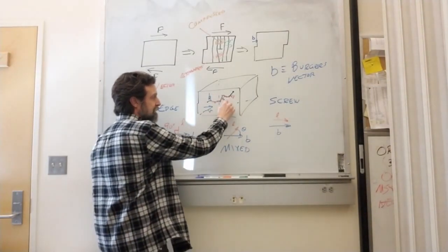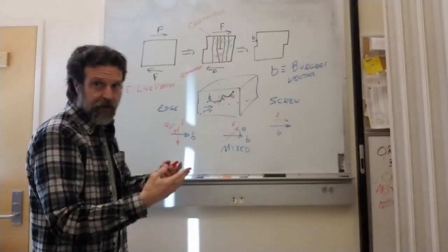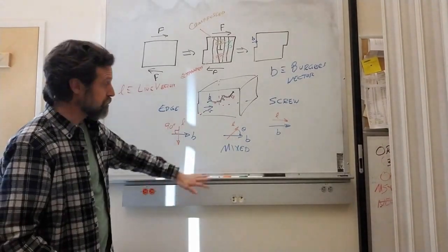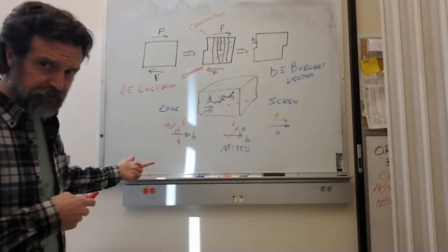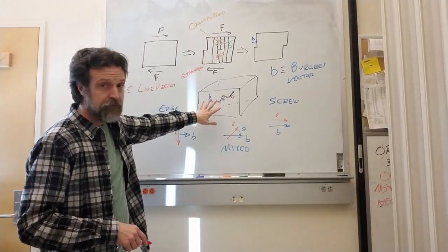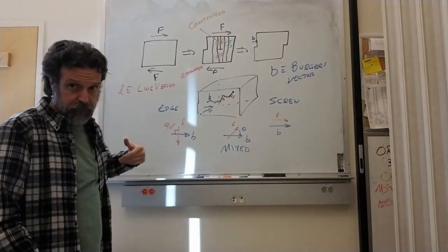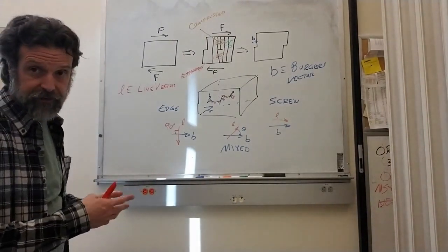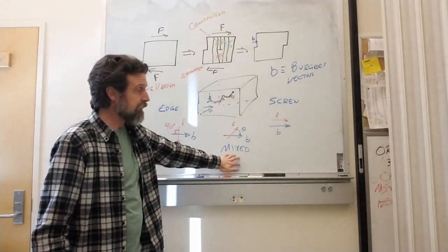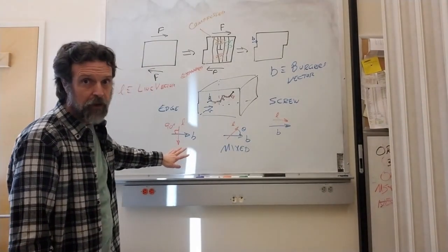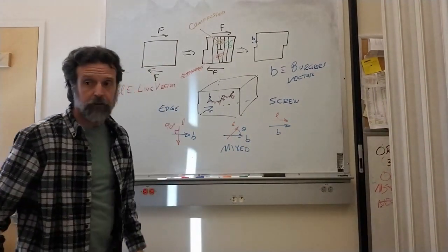But most of what's happening here is actually a mixed case, where the line and the Burgers vector are not exactly pure edge or pure screw, but a mixture of the two. The good news for us is that we described what's happening around the dislocation in terms of the elastic strain, and most of the time we can work within linear elasticity. We can simply take this mixed dislocation and talk about it as being a sum of the edge and screw components. So we can look at these a little bit.